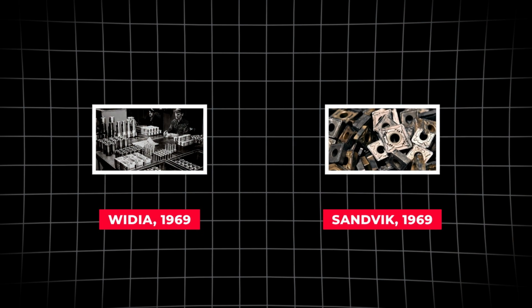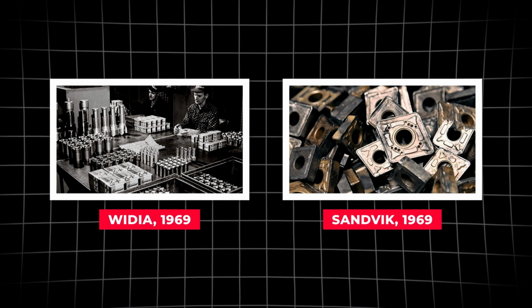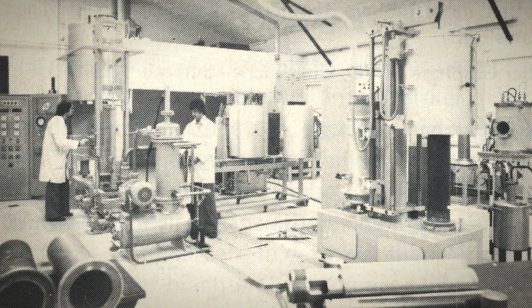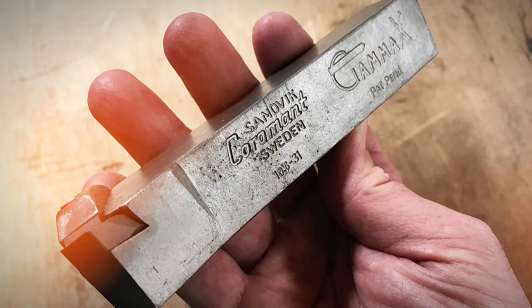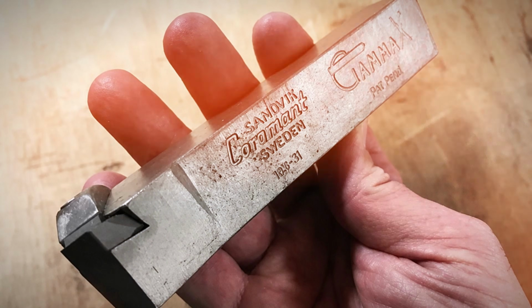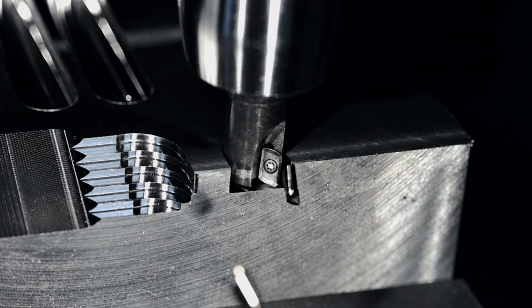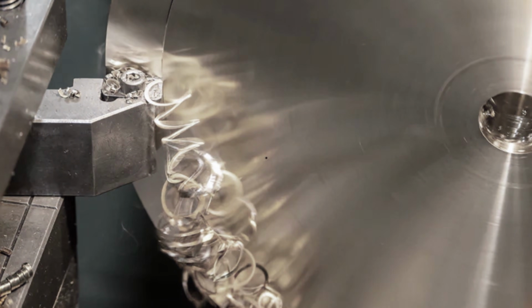In 1969, the first coated carbide inserts reached the market, from Widia and from Sandvik, within months of each other, each carrying a film of titanium carbide a few microns thick, laid down by chemical vapor deposition. Sandvik sold its version as the gamma coating and reported performance gains of up to 50%. The physics is simple and brutal.